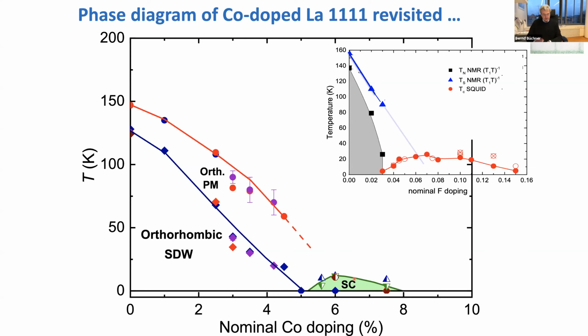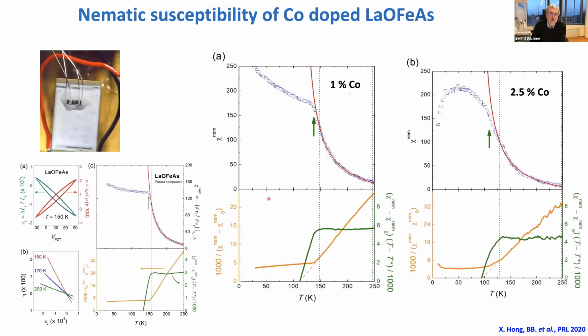So now let's start. We have single crystals at hand, so let's do more experiments. The first thing we can do, which is well established meanwhile, is nematic susceptibility measurements. What we measure here is the strain derivative of the resistivity. We have crystals glued on top of a piezo. We measure the strain, we measure the change of the resistivity, plot resistivity as a function of strain, take the derivative, and we get the nematic susceptibility.